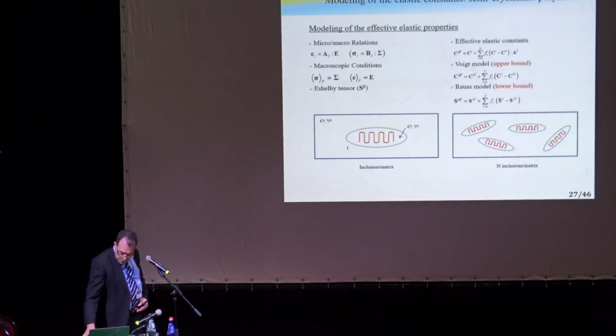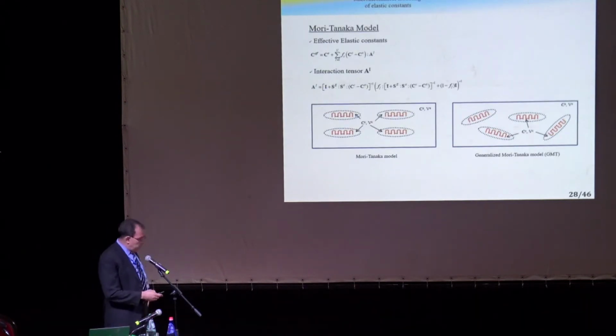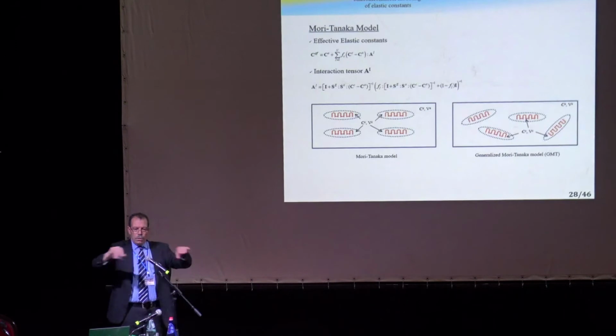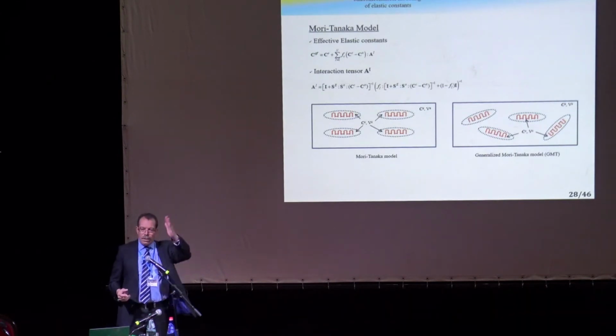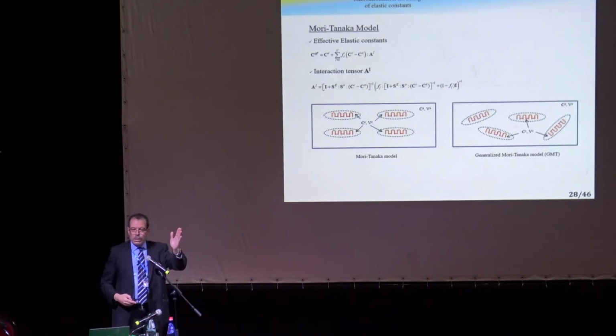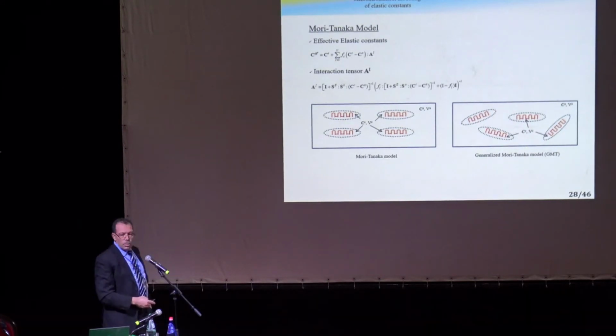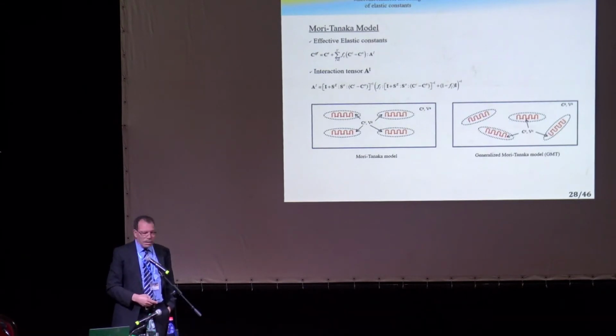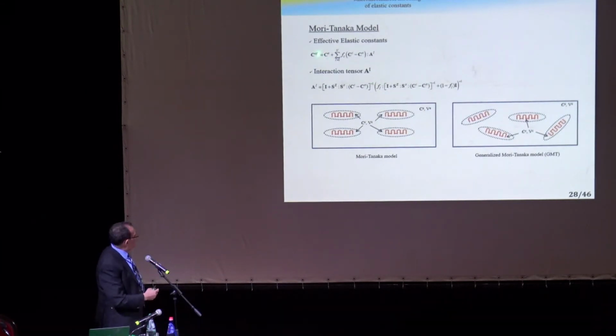We can also use the Mori-Tanaka model. This is the classical Mori-Tanaka where all the inclusions are parallel, but here the inclusions are ellipsoids, very elongated, and they are not in the same direction, they are all oriented in different directions. That's why we need to use the generalized Mori-Tanaka, which was developed in '87 by Benveniste, I think. Here the reference medium is the matrix, and the stiffness of the matrix is multiplied by this term, and this interaction tensor is given by this relationship, which depends on the Hill tensor.